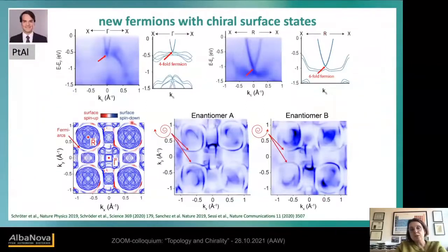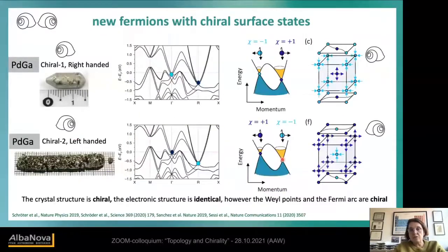And then you do what you do, you look for your photons. Here we see the 4-fold degenerate fermions, and here we see the 6-fold degenerate fermions in angle-resolved photoemission. And you see a nice agreement between the calculation and the photoemission. We can make both enantiomers. They look in the band structure exactly the same. But if you look very carefully on the surface, because the band structure for both enantiomers is exactly the same, as I said, the phase is different.